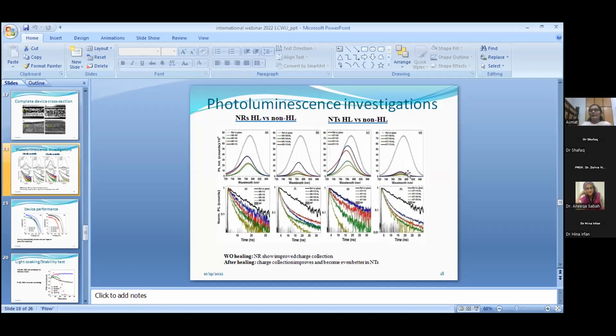And similar trends we can see in the time resolved spectra, that we have a better charge extraction in the nanotubes with healing rather than without healing. But one thing is interesting here, that without healing, the nanorods show an improved charge collection. If we compare the nanorods without healing and nanotubes without healing, we can see that the nanorods have better charge extraction than the nanotubes, because we know that the crystallinity of the nanotubes is affected due to the strong acidic medium. And after healing, we can see that the charge collection improves and becomes even better in the nanotubes.